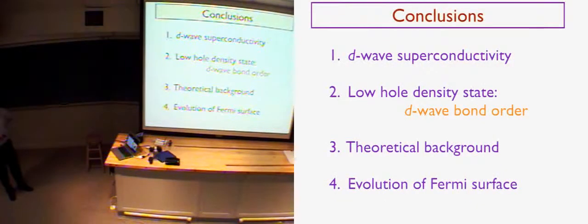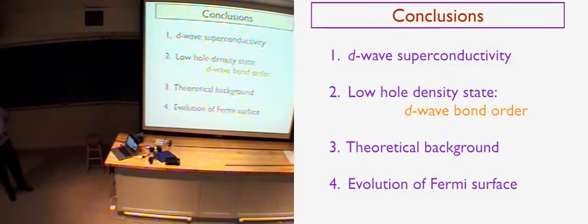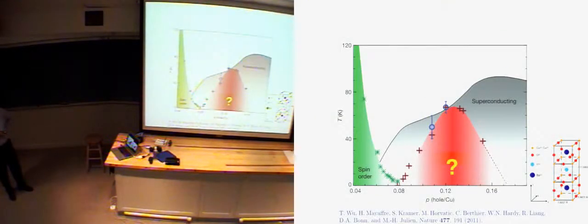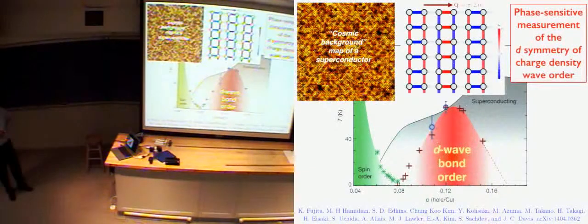So finally, in the last couple of minutes — in the next month's issue of Science there are a couple of STM papers looking at what's happening, looking at the Fermi surface. Both papers see — this is my colleague Jenny Hoffman's paper — and what they conclude from pictures like this is that in this region the Fermi surface is these arcs, just as I showed you. At high doping when there's no charge density wave, you get these new features telling you that it becomes the full Fermi surface. So there seems to be very clear evidence of at least a phase transition in the structure of the Fermi surface right there. The Seamus Davis group also has a companion article in the same issue of Science seeing the same thing — going from arc-like features to the full Fermi surface.